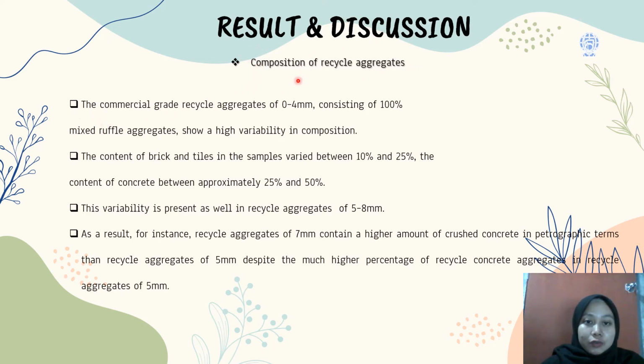The result and discussion of this is that the commercial grade recycled aggregate of 0 to 4 mm, consisting of 100% mixed recycled aggregate, shows a high variability in composition. The content of brick and tiles in the sample varied between 10% and 25%, and the content of concrete between approximately 25% and 50%.